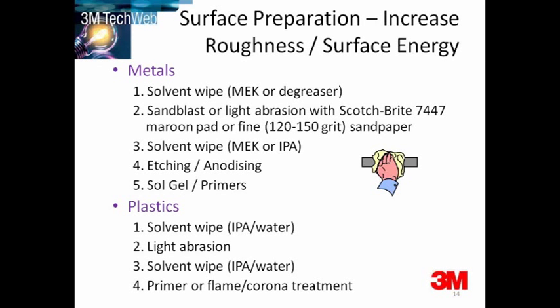Products that are used in harsh environments, with demanding loads and safety critical applications, will almost certainly require more vigorous surface preparation compared to an indoor application with little load. The aerospace industry spends millions of pounds each year anodizing and etching metal surfaces to ensure the highest level of joint performance. Indeed, most planes these days are actually bonded — the strength comes from these bonded joints, which some people don't know. Surface pretreatment is indeed specific to the surface.